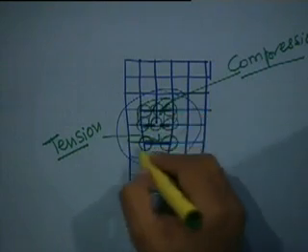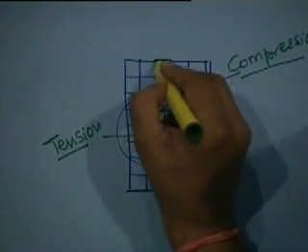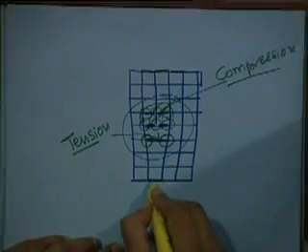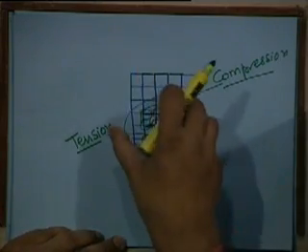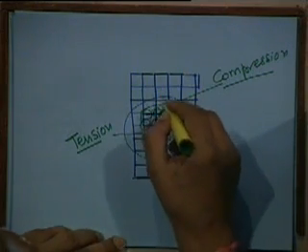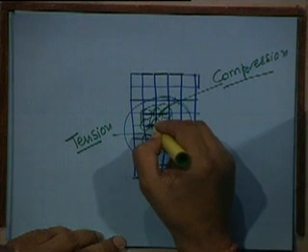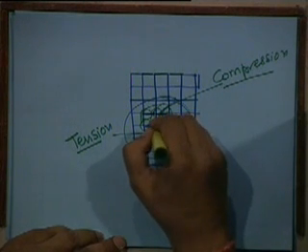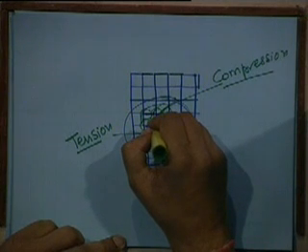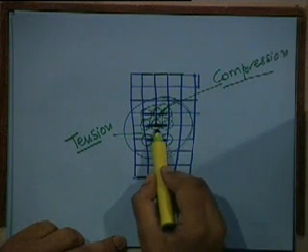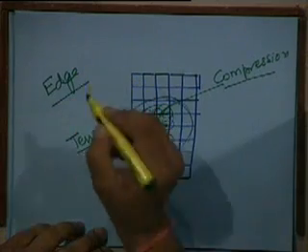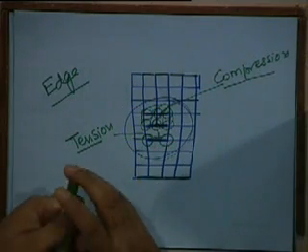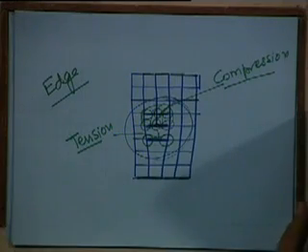But as I go away from this region, I don't find that problem here. They are the usual lengths as I go away from there. But these strains in the bonds are present only in this region, which is around this place. What is this place? The termination of the plane. So I call it the edge of the half plane, and this edge of the half plane is what I refer to as edge dislocation. Please make this configuration by hand to understand this better. We shall start from here the next class.